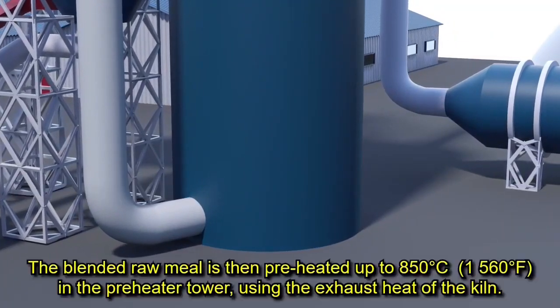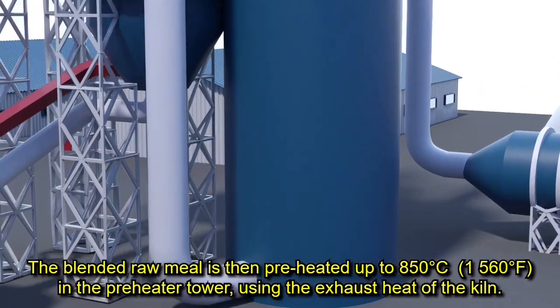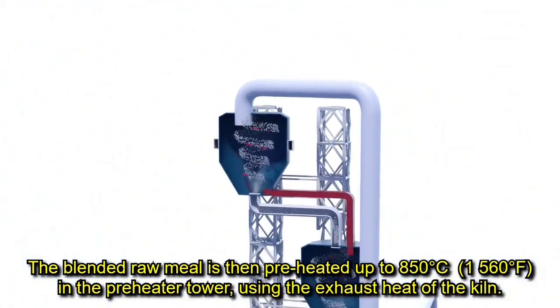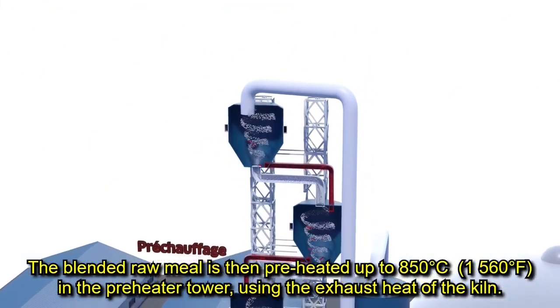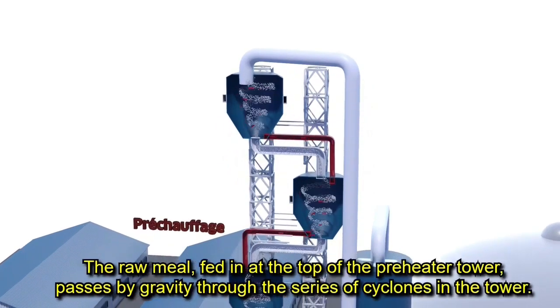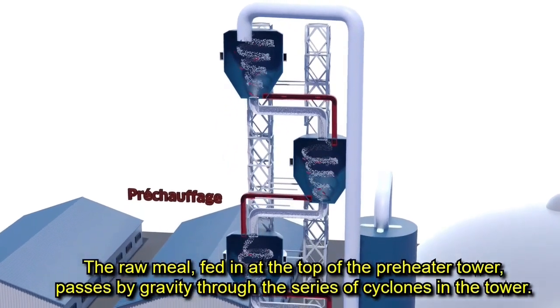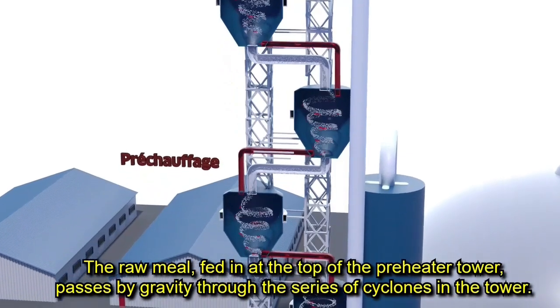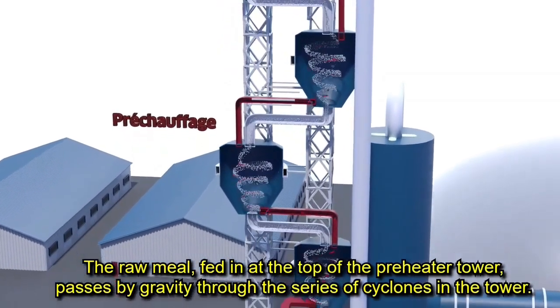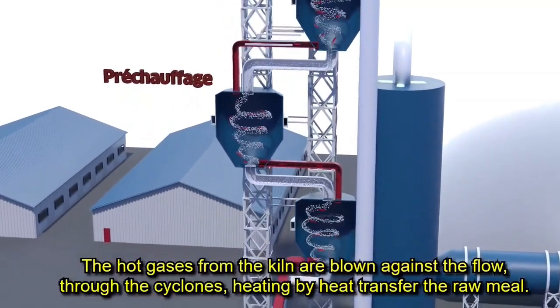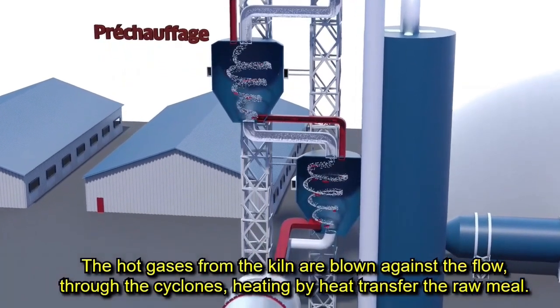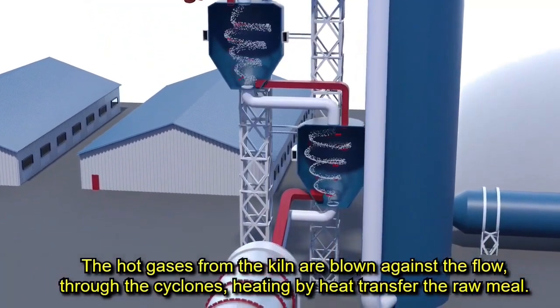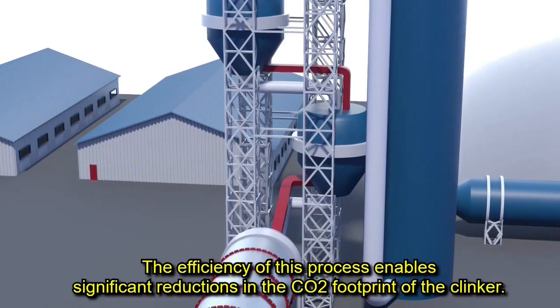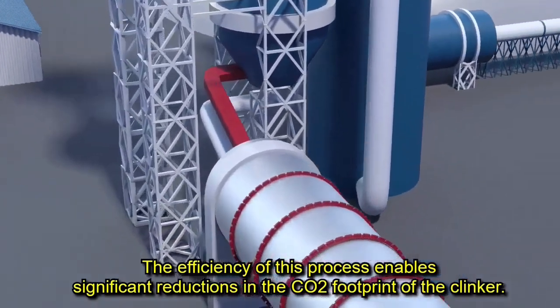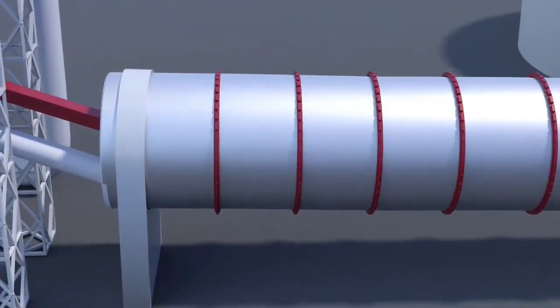Preheater. The blended raw meal is then preheated up to 850 degrees Celsius in the preheater tower using the exhaust heat of the kiln. The raw meal fed in at the top of the preheater tower passes by gravity through the series of cyclones in the tower. The hot gases from the kiln are blown against the flow through the cyclones, heating by heat transfer the raw meal. The efficiency of this process enables significant reduction of the CO2 footprint of the clinker.